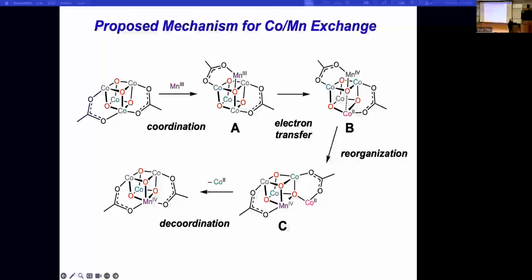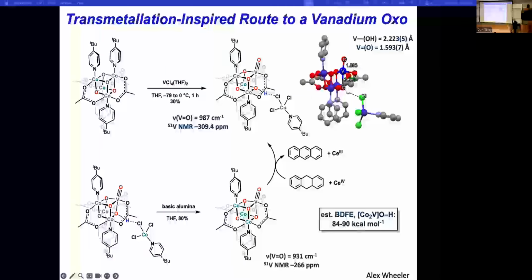So we do have a couple of new cubanes that we've been able to make this way. It could be that all you need to do is bring in an electron, so a reducing metal. And so we've seen it work in a couple of cases, in addition to what I just showed you. One has to do with vanadium. So vanadium 4 reacts under conditions that supply protons and a little more oxygen. That has to do with the conditions that have to be used for this, but it installs a vanadium 5 oxo unit in one corner.